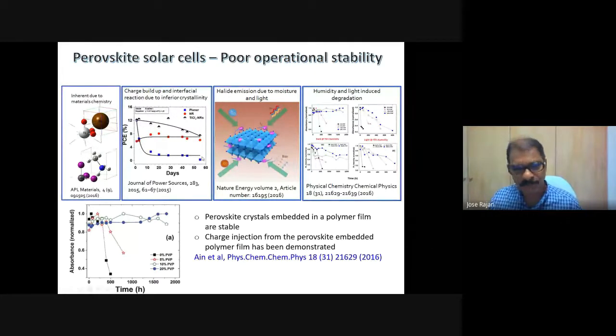Another thing that we have tested is what happens when we encapsulate the perovskite in a polymeric matrix. We have shown that when we encapsulate the perovskite in a polymeric matrix, we can actually enhance the stability. You will see this blue one, the absorbance. It is really stable even after 2000 hours under normal conditions.